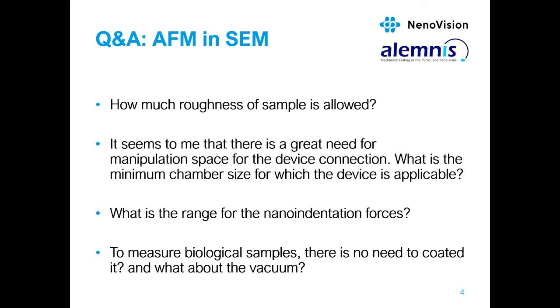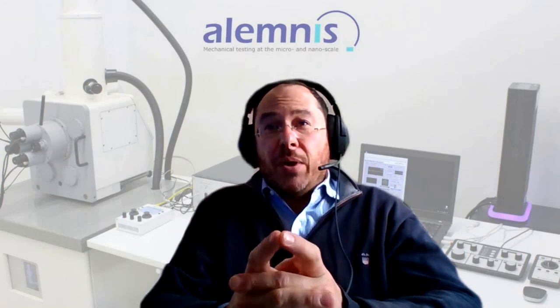Okay, there's a question from Navid. Why do we get a higher Young's modulus by nanoindentation than the ultrasonic or tensile testing? So one of the reasons for that is that you're measuring a much smaller volume of material when you do nanoindentation. So you may have surface effects. Let's take, for example, a piece of steel. If you've polished that piece of steel, then the near surface region is probably going to be harder, and it may have a higher modulus because you've polished that piece of steel, and so locally it's work hardened near the surface. That could be one explanation.